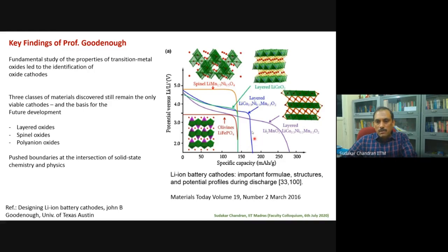In this particular picture, the three compounds are shown. In addition, there are two other compounds. NMC is shown, which is an improved version of the LiCoO2 layered compound. The manganese 1.5, nickel 0.5 spinel is another improved version of the spinel compound they came up with. Nowadays, people are looking at lithium-rich layered oxide, which is a slightly modified version of the layered oxide. It shows close to 200, 250 or more than 250 milliampere hour per gram. But there are issues with cyclability and so on. So current research is mainly about how to mitigate those losses.